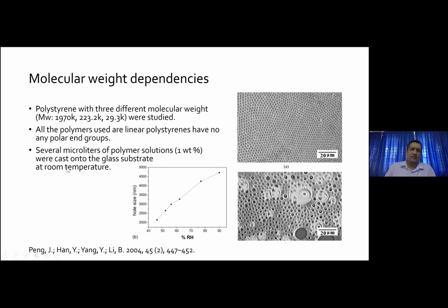And as a function of the relative humidity, if you increase the relative humidity, obviously the pore size is expected to be larger because you tend to have more droplets nearby, coalescing, and so on. So this also has been done at 1% concentration of the polymer solution, from very low relative humidity to very large relative humidity.